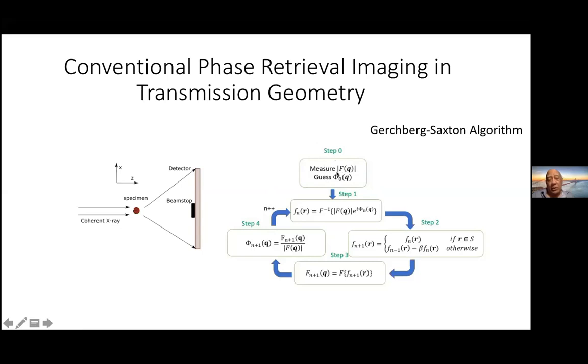This is the scattering amplitude, and it has a phase, phi naught of q. You measure it q by q. If you could measure the phase and invert it, you'd get the electron density of the object, and you'd have the image. But you don't know the phase. So what you do is, for every q, you guess a phase randomly. And then you Fourier transform it back to get a real space fictitious electron density. And then you make sure that this electron density satisfies certain conditions.